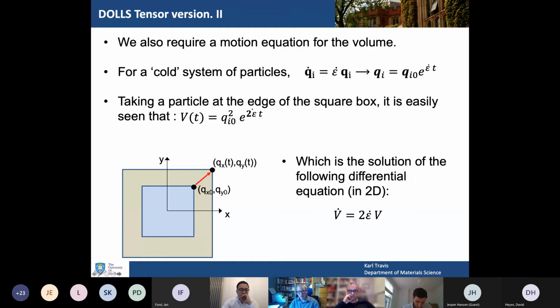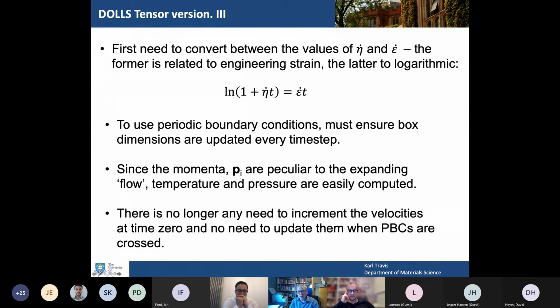So you've now got a complete set of equations to model fragmentation in the same way that Holian and Grady did it. Now, you have to be careful here, because I did mention that I'd used a different symbol for the stretch rate or strain rate. In Holian and Grady's original technique, they had growing periodic box lengths, and they used eta dot. I've used epsilon dot. What's the difference between them? Well, it turns out one's related to engineering strain and the other to logarithmic strain. So there's just a logarithmic connection between the two.